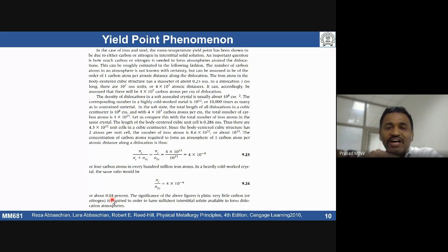Even if you go to the lowest carbon, extra low, ultra low carbon steels, we'll have at least 40 ppm carbon. So that's good enough. That means whatever steels you are producing, even of such low carbon, we do see this problem. If you get pure iron, people, Cottrell, said we don't see such a phenomenon. People did not report it also, because it's very difficult to get a ductile pure iron. People are producing it by different routes, but it's not ductile enough, because processing artifacts make it brittle.